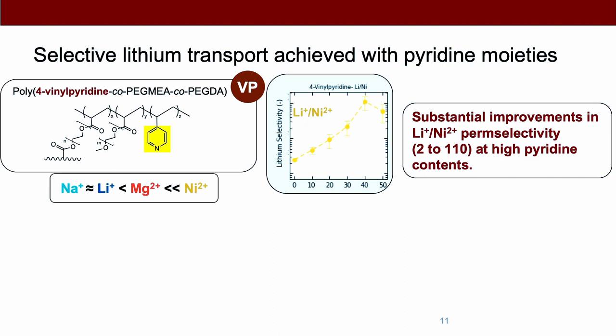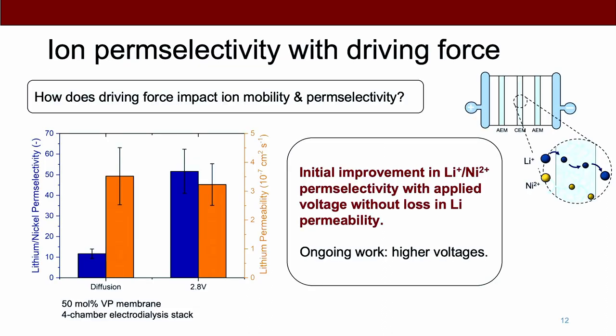Right, so we're getting like a 50x improvement, and we're able to really understand the sensitivity to the dose, if you will, the mole percentage of the membrane that we're interested in. We've also started to use electrochemical potential, moving from material to process, to say, what if I change the potential that I apply? Does that influence the selectivity I observe? And in fact, what we're seeing, at least initially, is that it does.